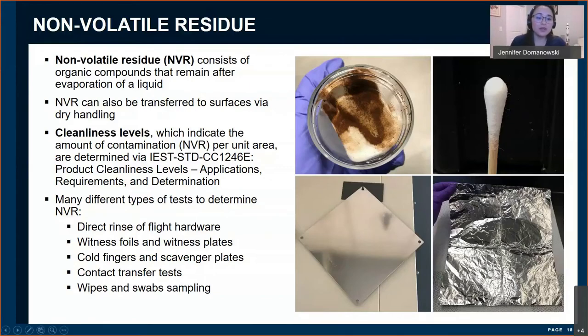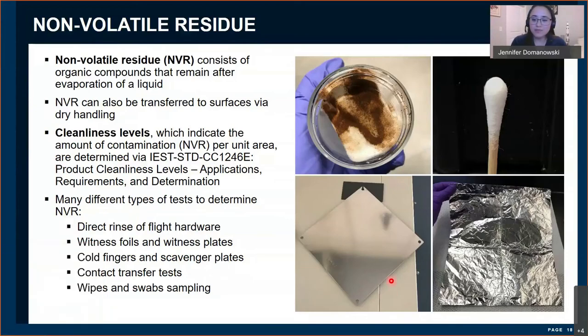You can use witness foils and witness plates. So this is a more passive form of collection. This here is a witness plate, and then this is a witness foil. So typically what you do with witness plates and witness foils is you hang them up in clean rooms or whatever space you want to monitor, and leave them up for 2 weeks, a month, however long exposure you want, and you then rinse them afterwards to see what has deposited onto it. So this is a way to monitor the health and cleanliness of space.